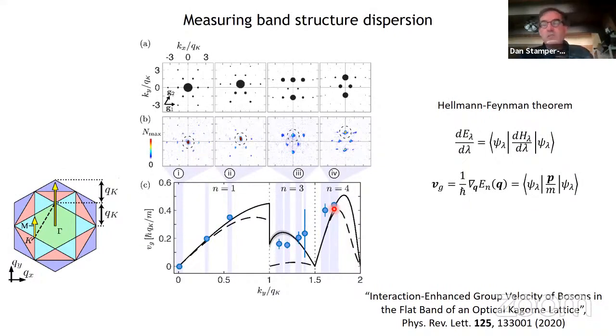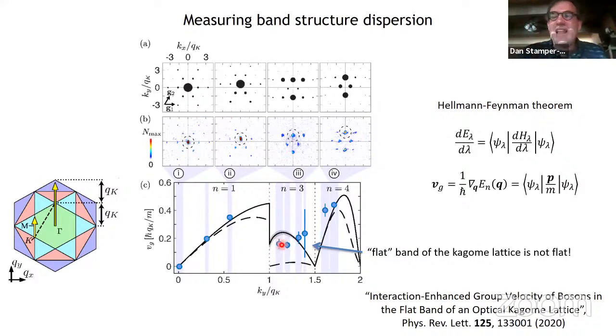Now, what's the prediction? From single particle physics, the prediction is this dashed line. And this dashed line tells us that the group velocity in the third band, the one that's supposed to be flat, non-dispersing, is basically 0. It's a little bit non-zero because we don't have a very deep lattice on right now. But anyhow, the flatness of the third band of the Kagome lattice should show up in a near 0 group velocity. But in fact, we measure a very large group velocity. So this tells us that the flat band of the Kagome lattice in our experiments is not flat at all. It's highly dispersing. Now, why would that be the case?